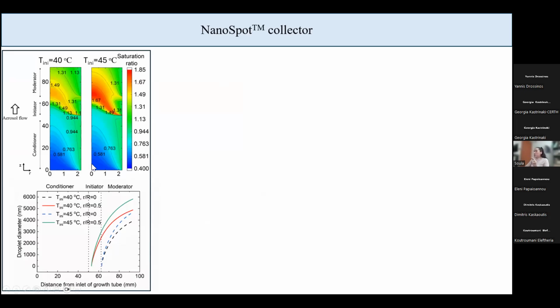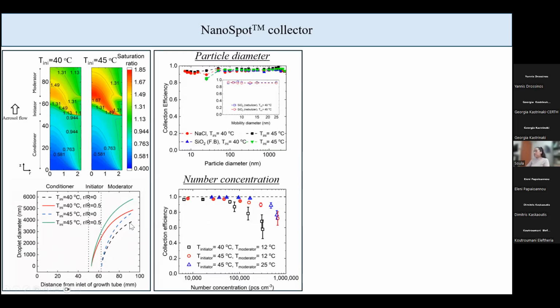In both cases, we see that we can get a saturation ratio greater than 1, which is required for activation and growth to happen. In the second plot, we can theoretically calculate the size of the droplets across the length of each of the growth tubes. And we see that in all cases, the smallest droplet size that we will get at the exit of the growth tube is going to be greater than 3 micrometers, very easily collectible.